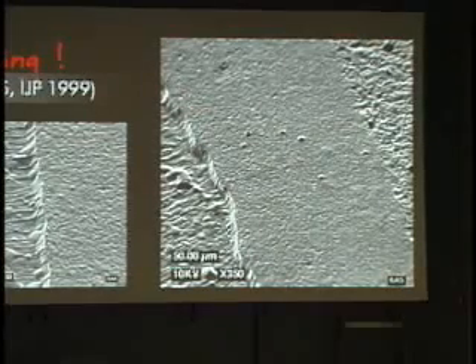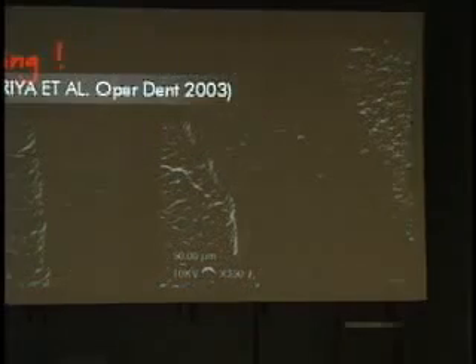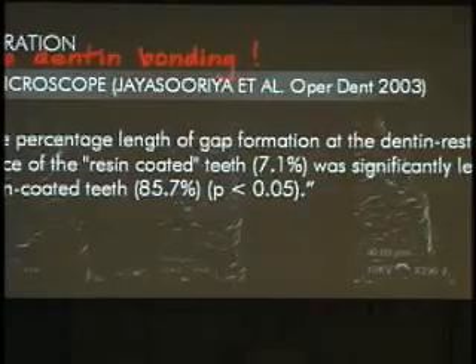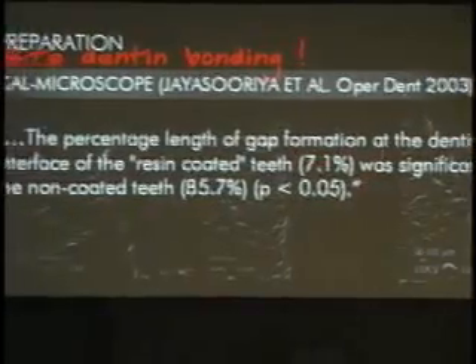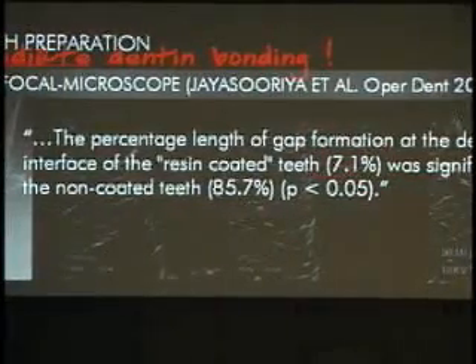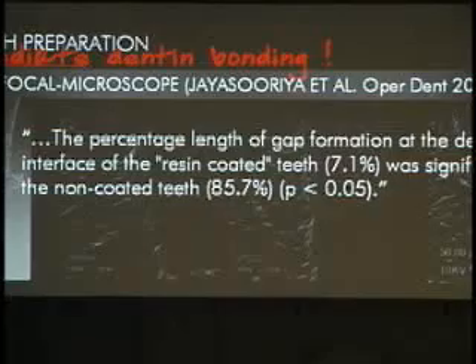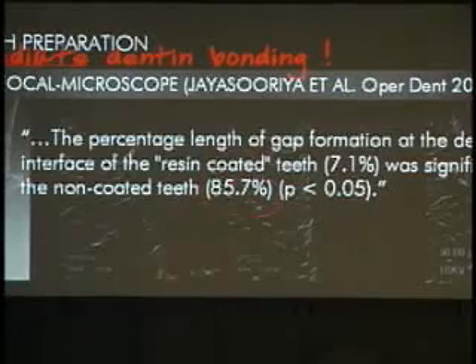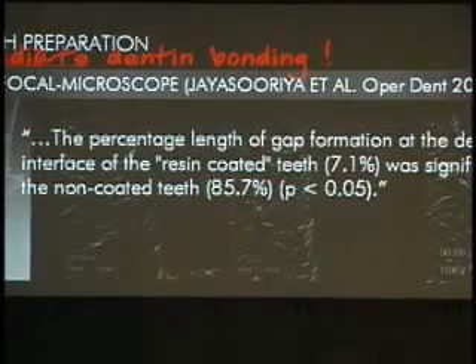If you seal dentin, that's what you are going to see, a completely closed gap. Other studies, using confocal microscope, show that resin-coated teeth, the so-called immediate dentin sealing, is able to almost close 93% of the gap, while if you don't seal dentin, you have completely opened internal interfaces.